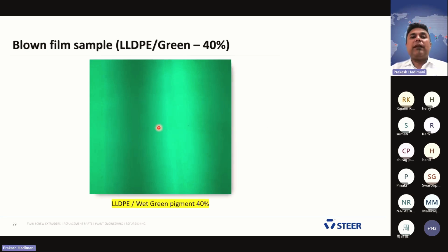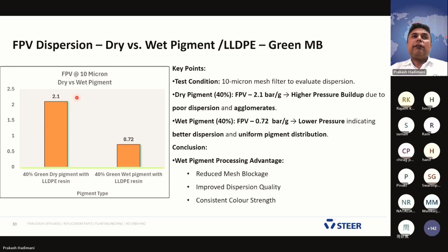We also did the blown film. We didn't find any agglomerated particles in the blown film. For the filter pressure value, on the left hand side, we used the same 40% dry pigments with LLDPE, and we observed a filter pressure value of 2.1 bar per gram. We used 10 micron in that, and the wet pigment showed 0.72. Okay, 0.72 filter pressure value using 40% green wet pigment with the LLDPE.